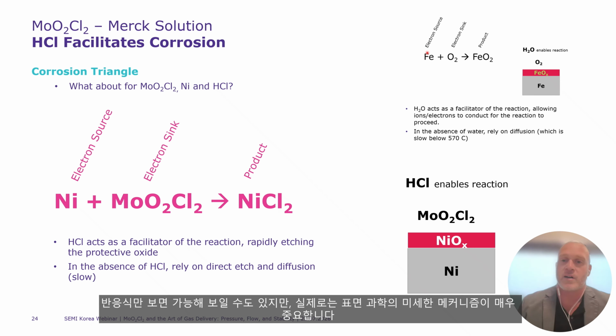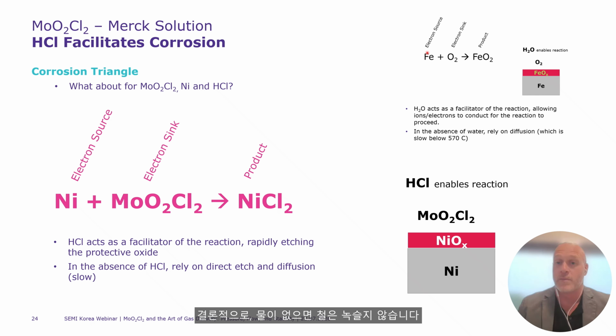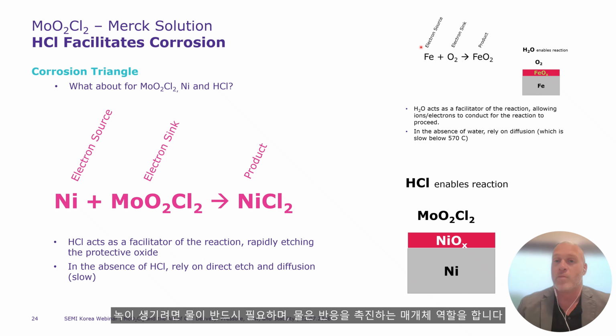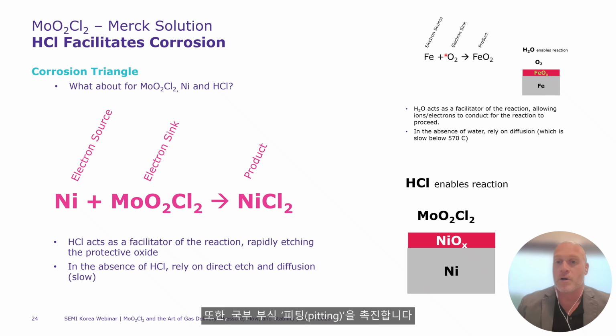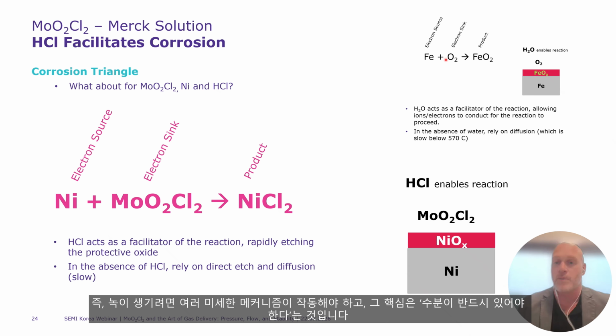But that's where the nitty-gritty details of the surface science and what's actually happening matters a lot. So fundamentally, iron does not rust in the absence of water. You need water, and water fundamentally acts as a facilitator. So it's an electron highway to be able to get electrons from your iron to your oxidizer, your oxygen. It also aids in pitting. So once you get that oxide layer, it degrades that oxide layer. So there's lots of small mechanisms that drive. You have to have moisture present in order to rust. So why does that matter for us?